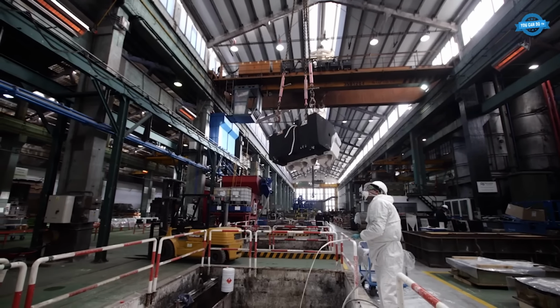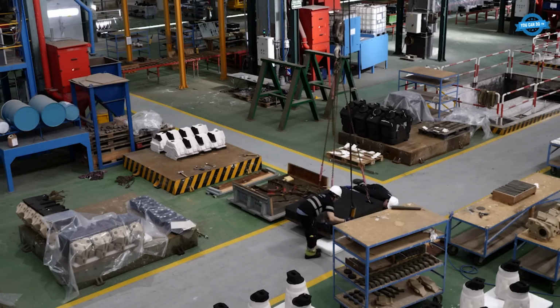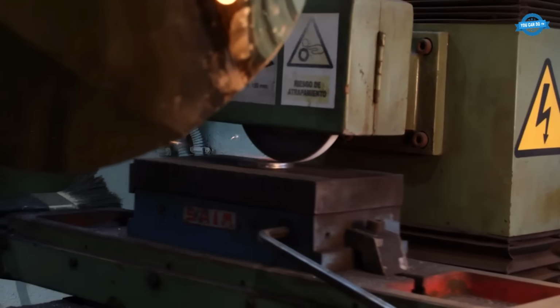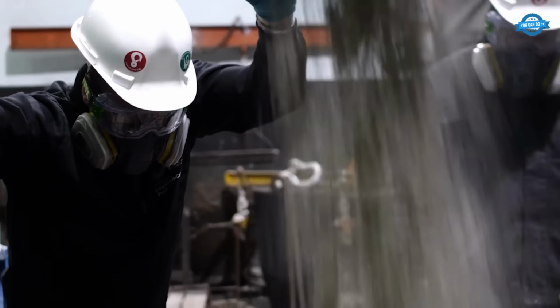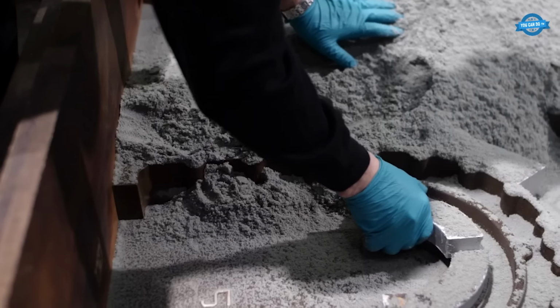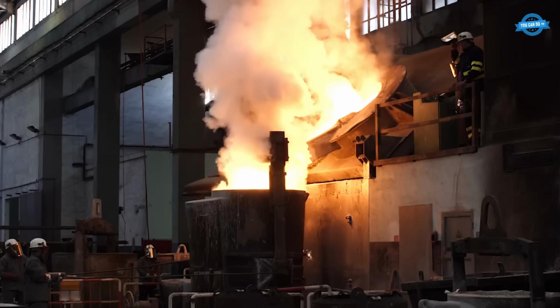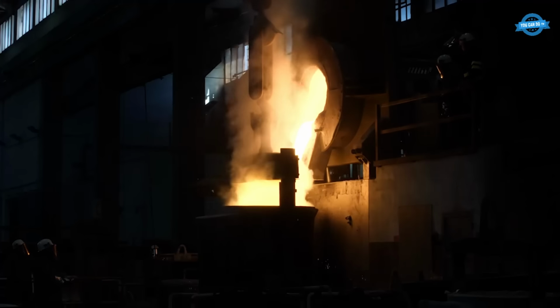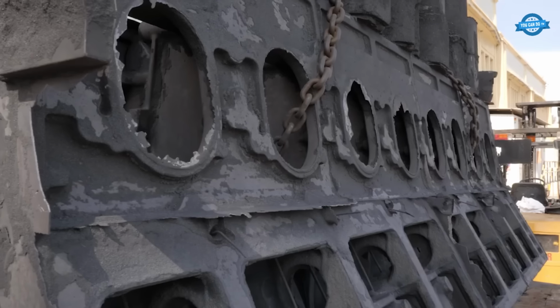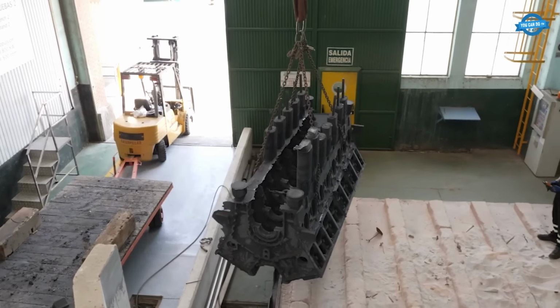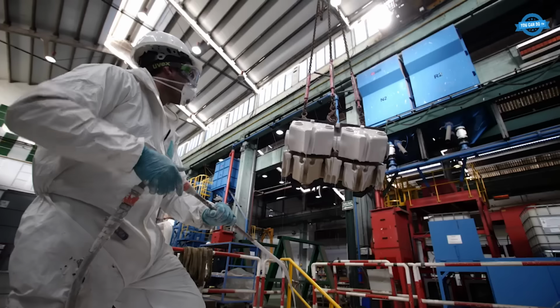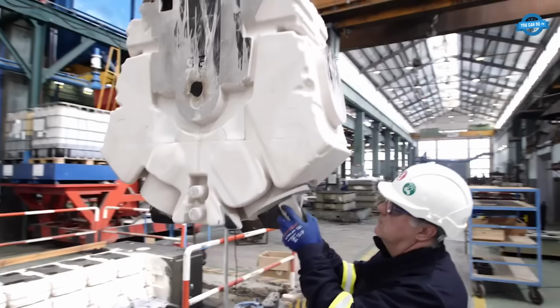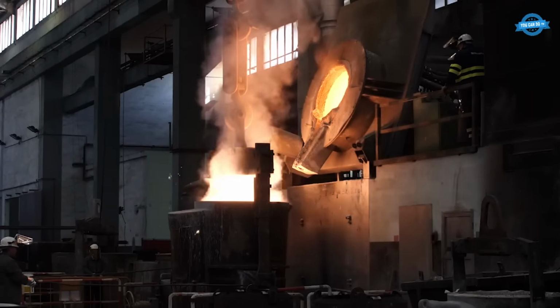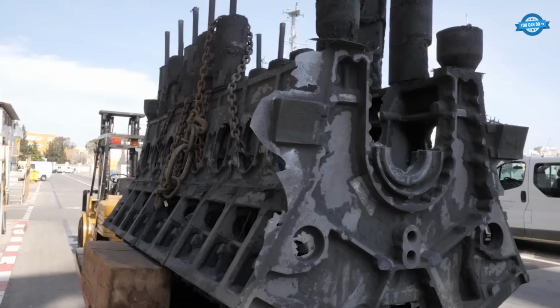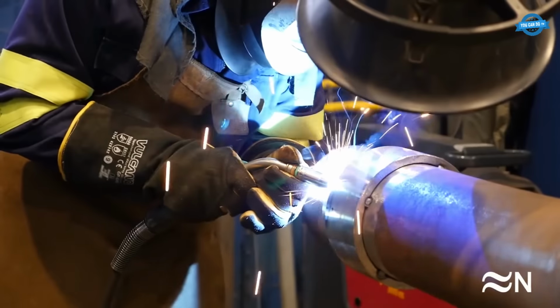The foundry casts engine blocks and cylinder heads for every major diesel engine the factory produces. Chemical bonded sand molds get formed from silica sand mixed with resin. Coating gets applied to the mold surfaces to improve finish quality. 3 induction furnaces melt gray and nodular iron. Casting temperature gets measured at each pour. A dedicated laboratory analyzes chemical composition of every melt in real time. Finished castings then move to a heat treatment furnace, because raw cast iron is brittle and heat treatment is what makes it a working engine block.